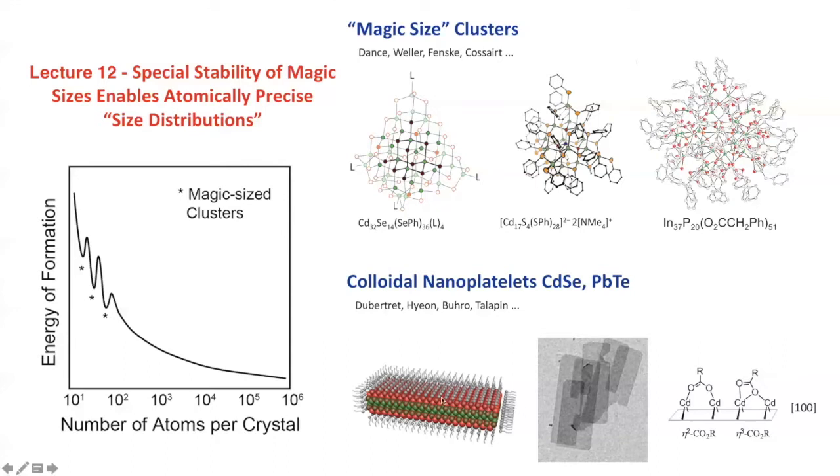So the reason these platelets form, as I mentioned in the past, is really about the binding of ligands and the binding of carboxylates with a small R group to the 1,0,0 facet. Acetate makes these types of crystals stable because it packs well. And so, minimizing the surface energy or really taking advantage of the strong metal ligand bonding gets you into these type of structures.